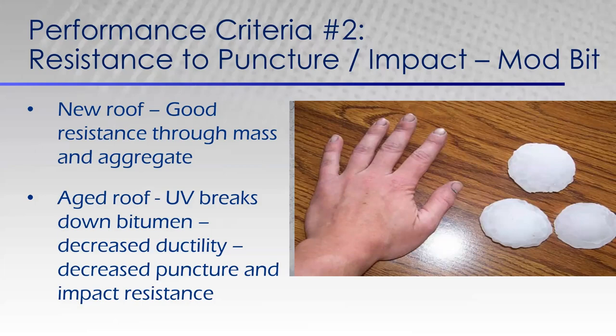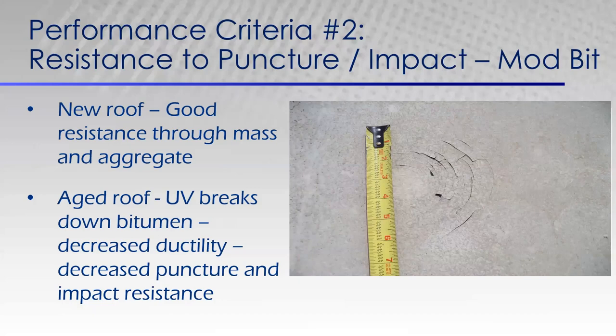As you'll see here in the next picture, a modified bitumen roof that has a coating on it. It's an acrylic coating. But as it was hit by a hailstone, which we measured to be about 3 to 3.5 inches, you'll see that it was no match for that hailstone and it actually caused some cracking of the coating of that modified bitumen system. So even as that roof ages, that UV breaks it down, those oils leach out, it decreases the ductility, and while the thickness may be good for impact resistance, puncture resistance really doesn't have too much of an impact with the thickness of the modified bitumen on the roof.